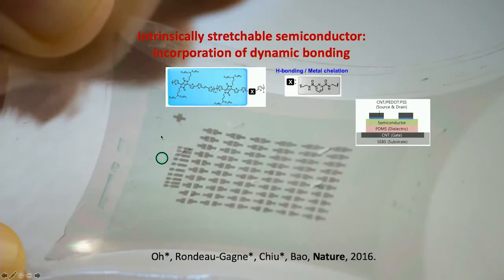So going from insulating material, just now, the material that I mentioned basically is a dielectric material. But going from insulating material to semiconducting material, it's actually more challenging because we have to, again, use these conjugated molecules, which tend to be rigid in order for them to transport charges. And also they form polycrystalline films, which again increase the modulus and make them even more rigid. So learning from the chemistry design that we used earlier, again, we use these hydrogen bonding to incorporate into our semiconductor design. And this results in semiconducting material that has charge carrier mobility that's on par with those of amorphous silicon. But at the same time, now they are able to tolerate strain even as high as 100% without breaking.